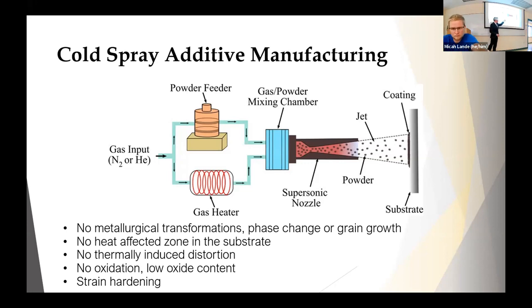Some of it also goes through the gas heater, which again, we're just adding energy into the system that we're going to use later. Then they mix together in the powder mixing chamber. And then in the entrance zone of our supersonic nozzle, you have immense temperature and immense pressure. As it goes through there, you go through that gas dynamic process, where at the very end your gas is going at supersonic velocities. And as it goes through, it also carries those teeny tiny powder particles along.